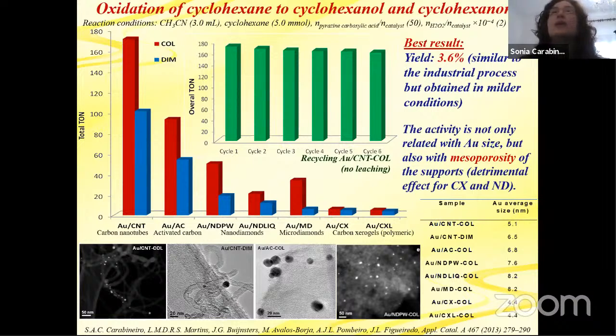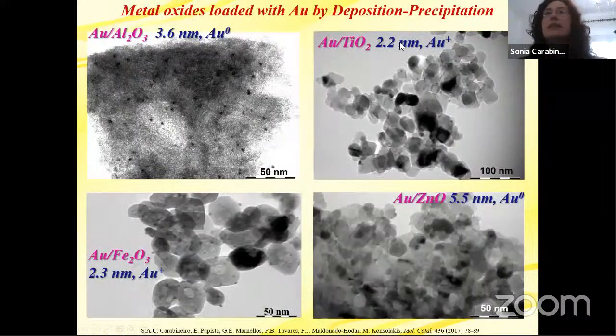Also, we have some gold catalysts here prepared by deposition precipitation. So on alumina, on titania, on iron oxide, and on zinc oxide. So we see here the sizes obtained. So the smallest are here, titania. And we had here gold 0, here gold plus. So depending on the support, the size of the nanoparticles and also the oxidation state change, even when prepared by the same method.